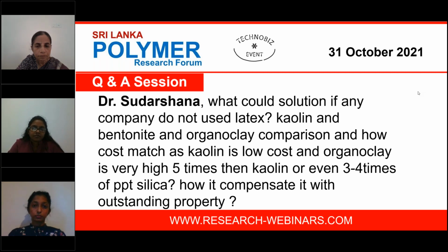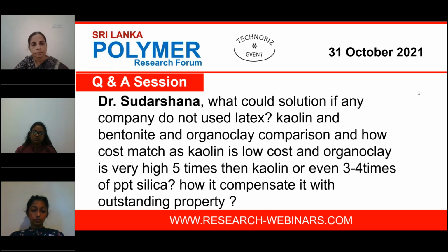So you can prepare organoclay from montmorillonite very easily. If you take organoclay from another company, then definitely for your formulation you have to pay a lot of money. But my recommendation is to prepare organoclay from montmorillonite, which is a very simple process. After that you can graft the silane 69 on that organoclay, which is also not very difficult. You need alcohol and a temperature of normally 60 to 70 Celsius. So I don't think organoclay is 5 times costlier than kaolin.